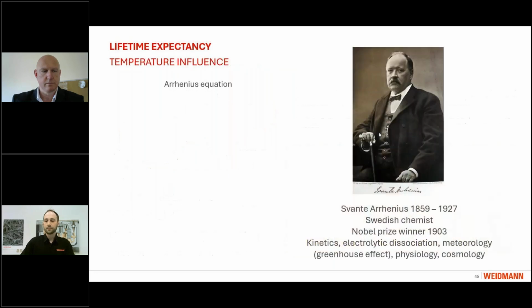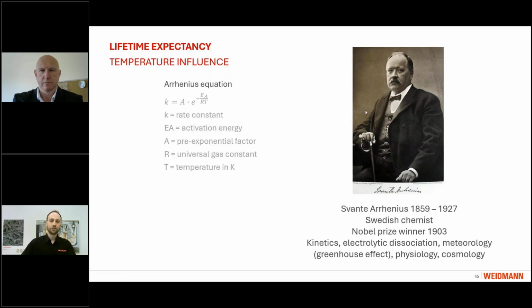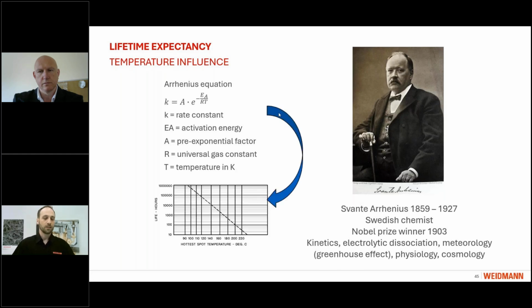So what is, again, the question here? The question is lifetime expectancy. And we can thank Arrhenius for his genius in finding the Arrhenius equation, which is an equation that determines the rate at which natural processes take place. Now we see that the rate is here this K, the A is a prefactor. Here we can state that this is mainly a material specific factor. Then we have the activation energy. This one depends on the process that takes place. And we can see, as so often, the temperature that plays an influence here. This temperature dependent rate constant will allow us to plot our life expectancy against temperature, because we see that at lower temperatures this process takes place less fast, and at higher temperatures it gets faster and faster.